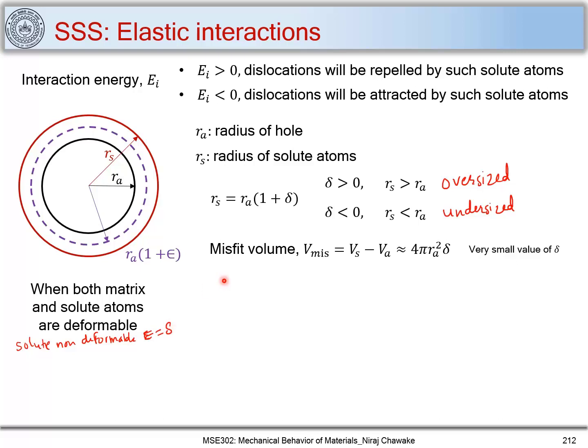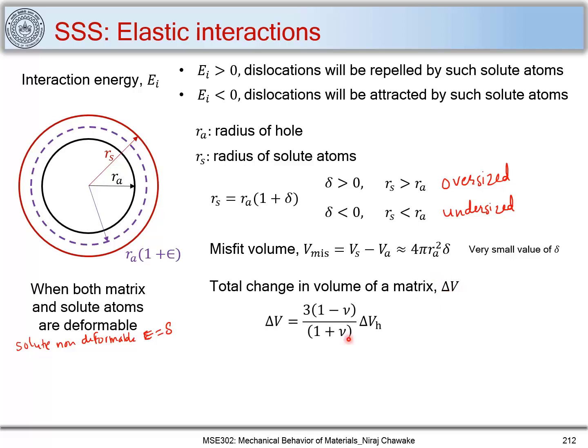There will be a total change in volume of the matrix due to this expansion of the hole or contraction of the solute atom when both are deformable. The total change in volume of the matrix, ΔV, can be expressed as 3(1 − ν)/(1 + ν) · ΔVh, where ΔVh = 4π·rA²·ε. This is a standard result available in any textbook.